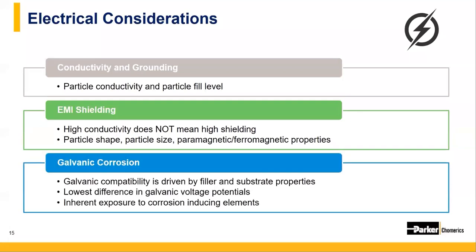And finally, galvanic corrosion applies when materials with different electrical potentials come in contact with each other in the presence of an electrolyte, such as salt fog or atmospheric moisture. With conductive coatings that have particles such as silver, nickel, and copper, there are bound to be voltage differences with the aluminum, the titanium, and the steel substrates. Fortunately, there are steps we can take to reduce the reactivity of these conductive parts.